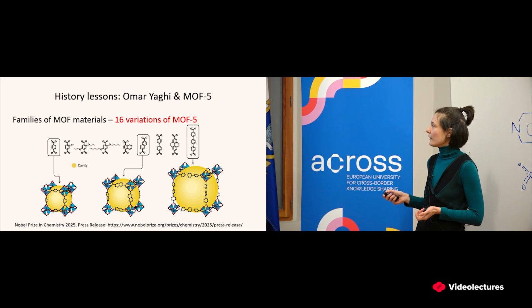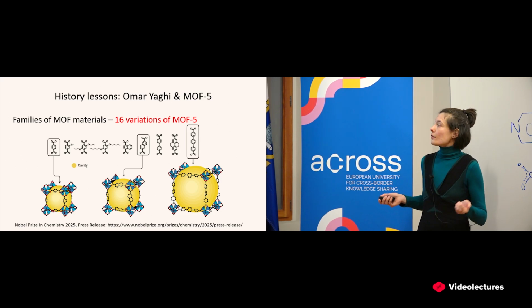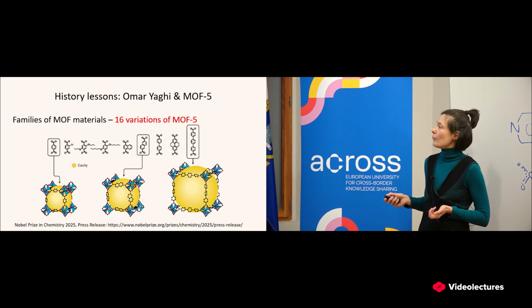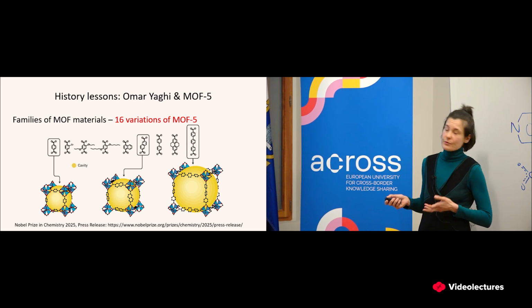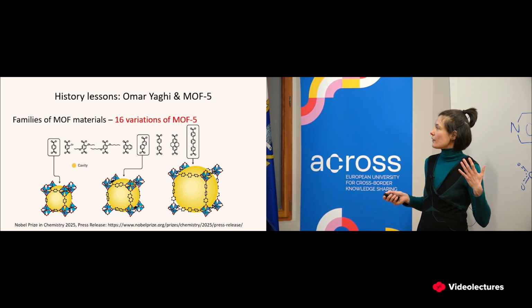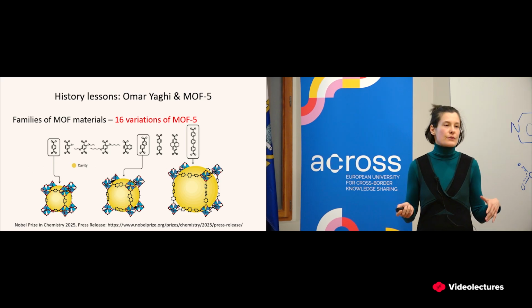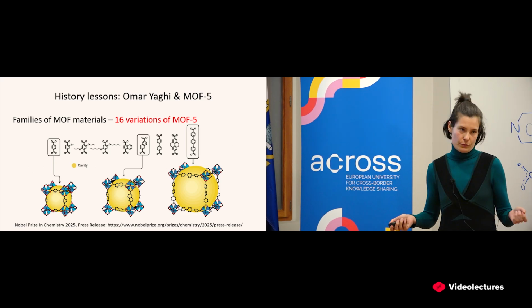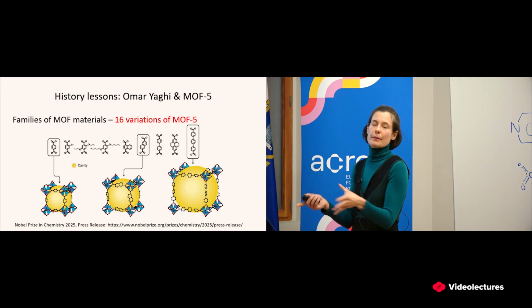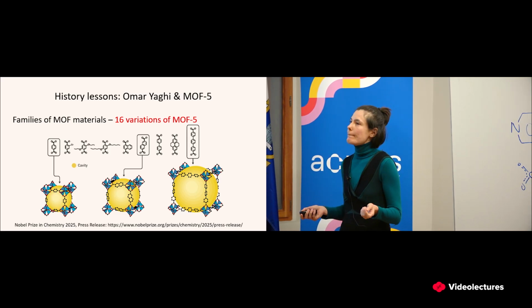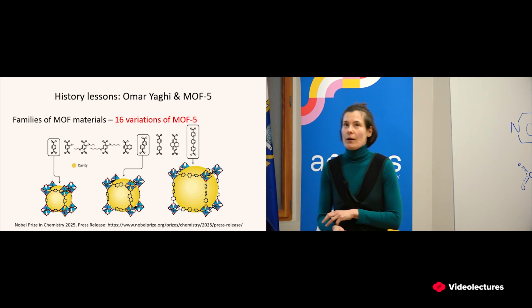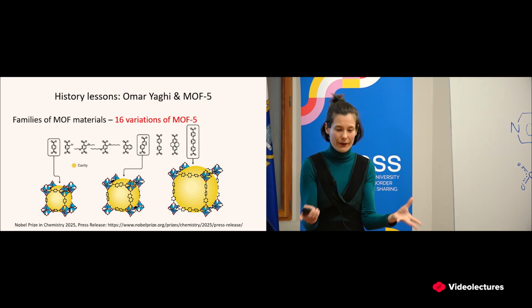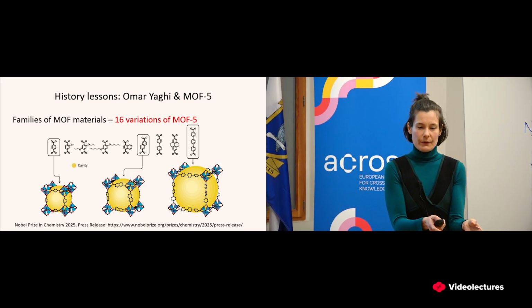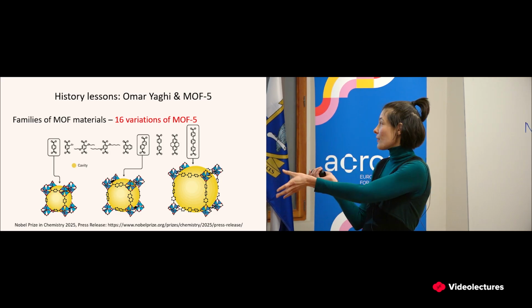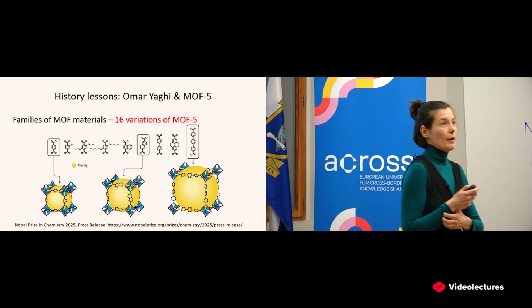But then if you use a slightly longer linker, the cavity size increases dramatically. You can also chemically modify this linker. For example, you can introduce different functional groups like halogen atoms, or introduce some hydrophobicity, and this will change the properties of the materials. Still, all of them have the same metal cluster in their structure. And this kind of predictability, where you can basically on paper or on a computer design a material and know its crystal structure, was not there before, right?